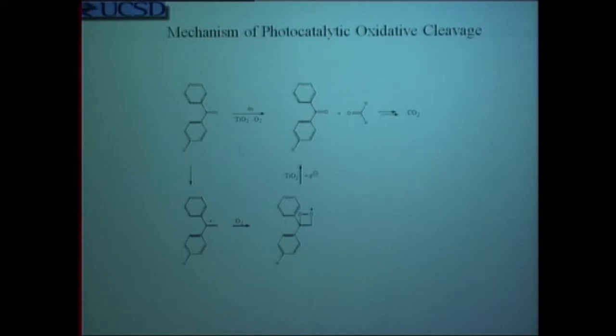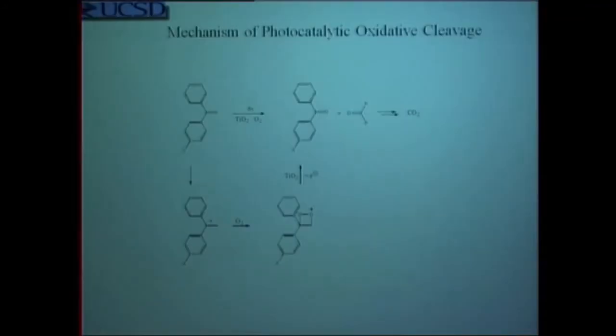This is typical of the kind of reactivity that one can examine by using photoelectrochemistry, because ultimately, if this is carried out again and again, notice that the products of this reaction have additional unsaturation, and because of that, they can undergo further oxidation. You could take any of these molecules at a given stage and stop the chemical exposure to light and have a synthetically useful material. The reaction shown here, at low conversions, selectivity is 100%. It's a very clean reaction. A solid suspended in a liquid with a reactant, expose it to light, filter out the solid, and you have your product. So it's a very simple way of going about it. And by using the tools of physical organic chemistry, you can even describe the expected intermediates that are formed.